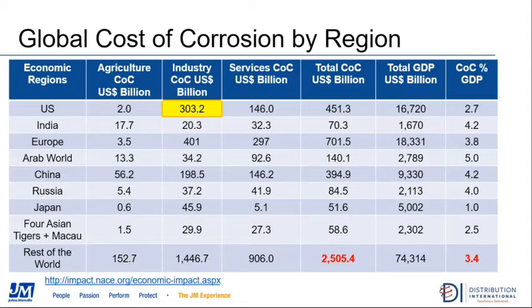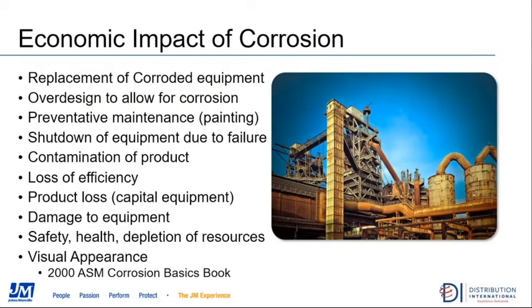More relevant to most of us here in the U.S. or North America, you can see the block that's highlighted in yellow, looking specifically at the industrial sector within the United States, showing that the cost of corrosion in this sector was a little over $300 billion. And that is out of a total of about $450 billion for all of the U.S. market segments, so representing about 2/3 of that total in the U.S., or slightly less than about 3% of the U.S. gross domestic product. So again, showing that the financial impact of corrosion under insulation is very, very significant.